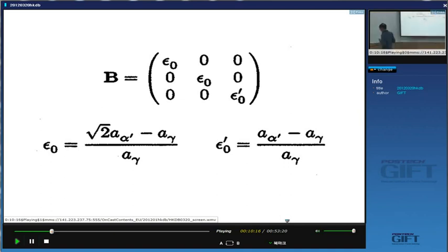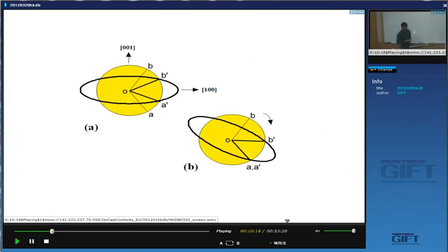Okay, so let's represent the austenite as a yellow sphere. This is my austenite, and here I'm plotting the z-axis, and this is the x-axis. So if I compress the austenite, then this becomes this ellipsoid here, and we have expansion along the x-axis, right? And what I want you to notice is with the Bain strain, we have these two lines here, which are actually cones in 3 dimensions, because we also have the y-axis pointing out of the plane of the board, which has expansion along the y-axis.